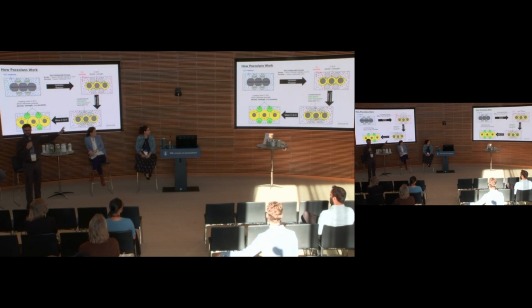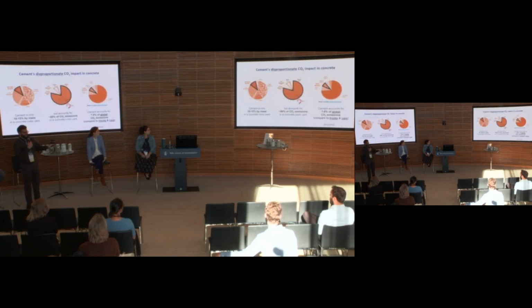I won't get into all the specifics, but this is just to show that Pozzolan is not an inert filler in the concrete. There is chemistry, there is a chemical reaction. The silica bonds with the calcium hydroxide, which would otherwise be porosity in your concrete, to create more strength, more calcium silicate hydrate. You can see the green circles there representing the strength crystals. And as Melissa talked about, there's a problem with cement, and that it accounts for 7 to 8% of global carbon emissions.